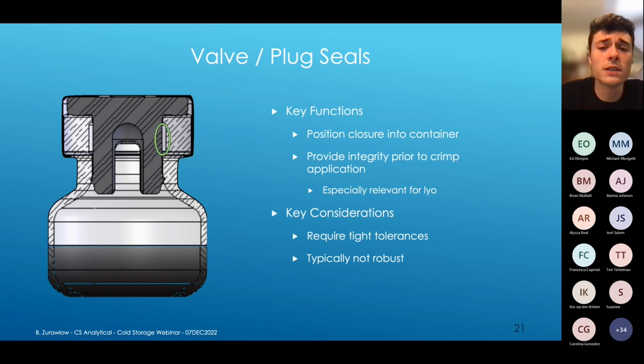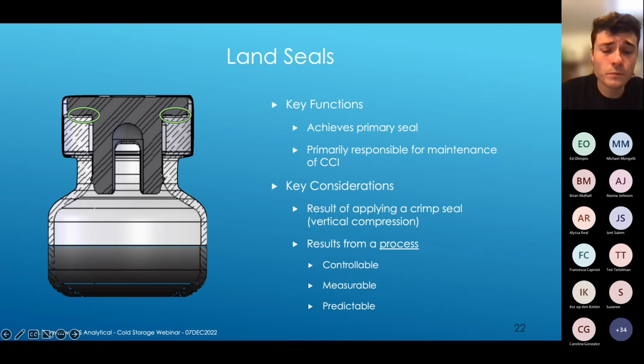And so considering each of these individually, this valve or plug seal, as it's referred to, its real function is to position the closure into the container prior to crimping. And in some cases, it can be relied on to provide integrity prior to crimping. This is something that's especially relevant for, let's say, lyo products, as it goes from that lyo chamber to the crimping line and must maintain that nitrogen backfill and under pressure inside that vial. So some key considerations, the efficacy of this seal is largely related to the tolerances of these component dimensions. And for that reason, it's typically not very robust as a seal.